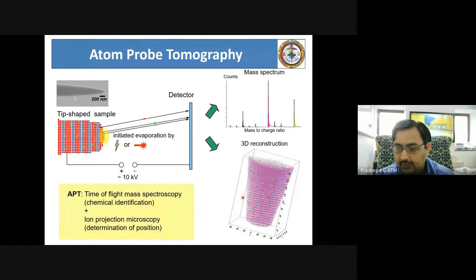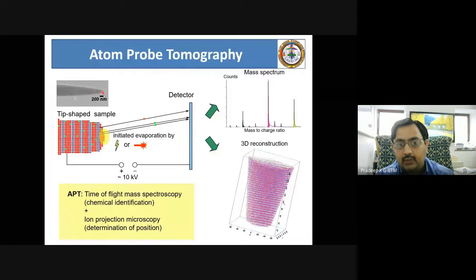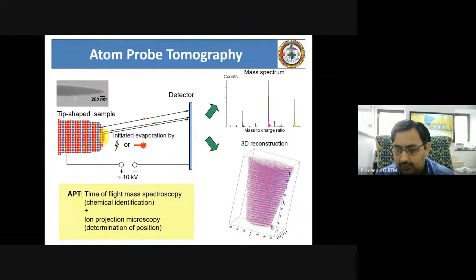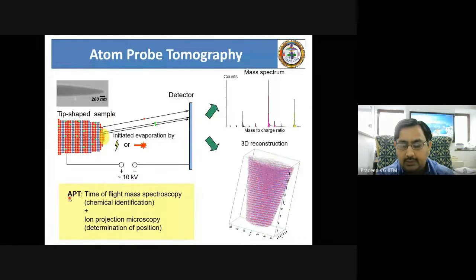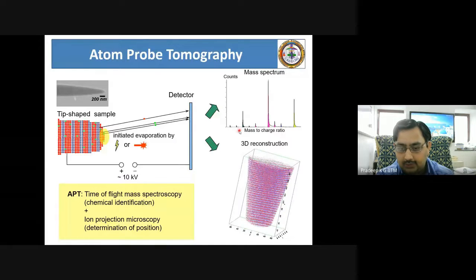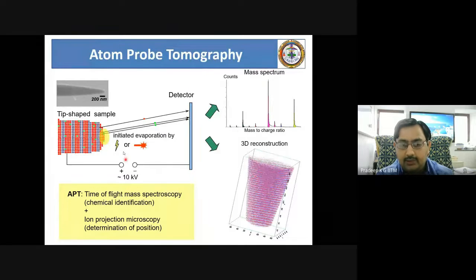And you can see at each of these layers, different chemical species are present, which was not possible to see in the original microstructure. But now you are atomistically resolved and you are able to see all the individual elements being 3-dimensionally visualized and separated for their chemical distribution. Therefore, this technique is quite powerful, where based on the time of flight, you identify the chemical nature of the material, and based on the ion projection microscopy, that means the projection over a distance, you see individual atomic positions, and therefore you are able to reconstruct them in a 3-dimensional form.